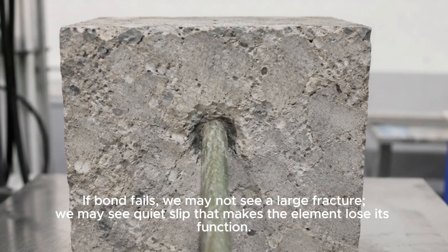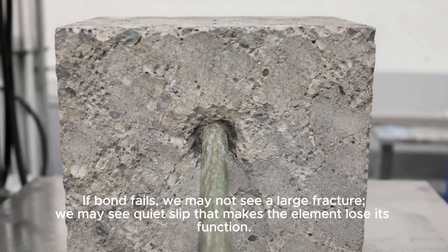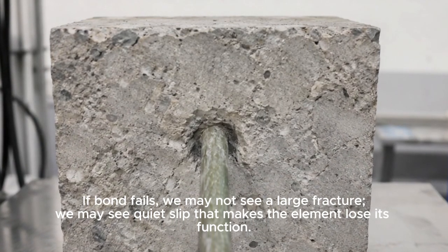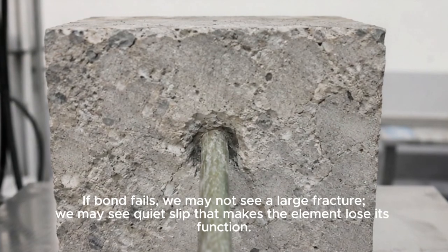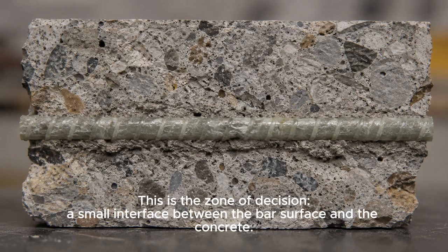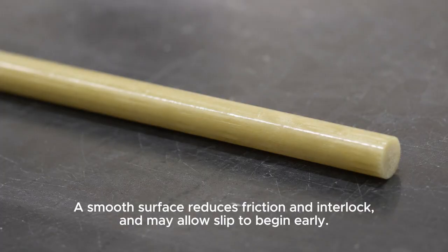If bond fails, we may not see a large fracture. We may see quiet slip that makes the element lose its function. This is the zone of decision, a small interface between the bar surface and the concrete. A smooth surface reduces friction and interlock and may allow slip to begin early.